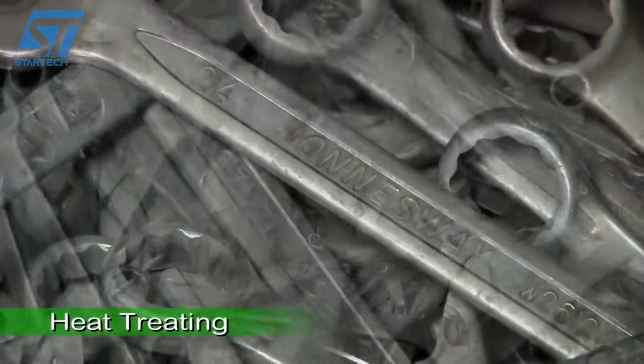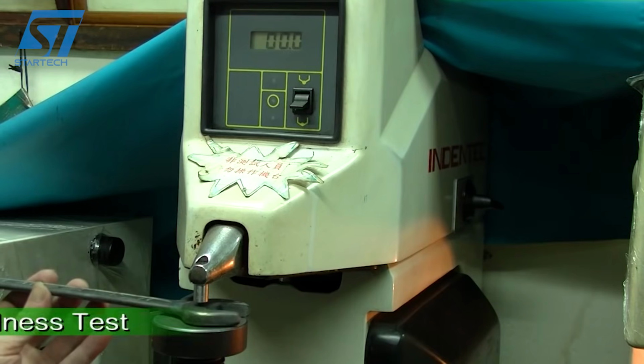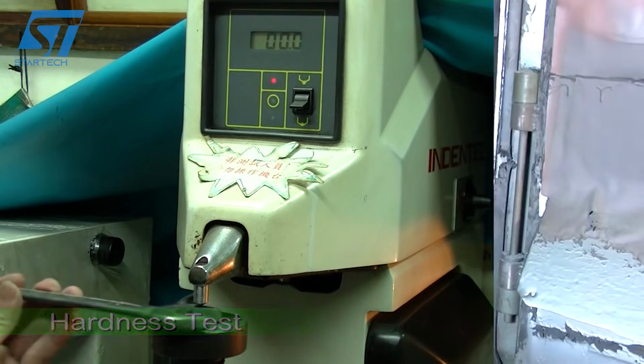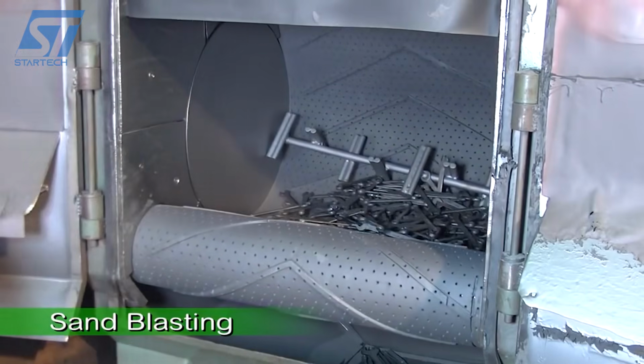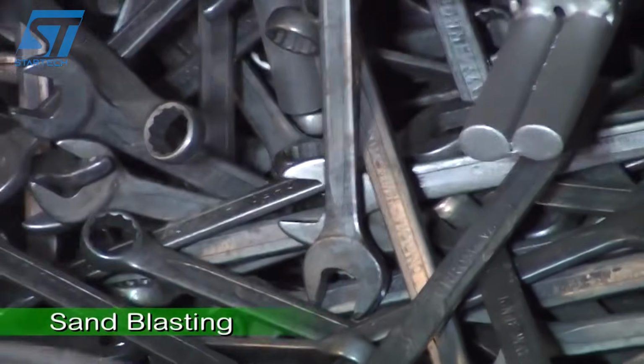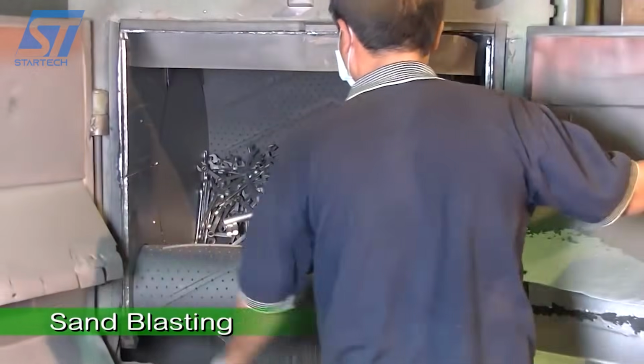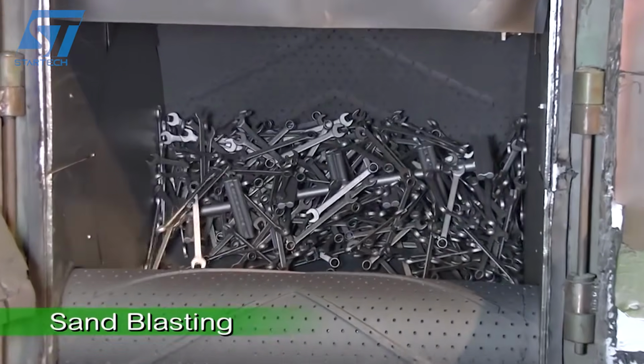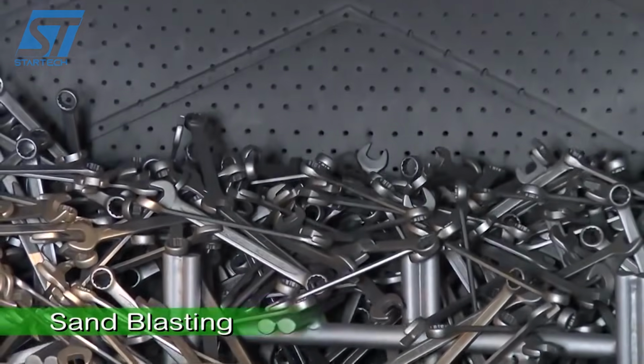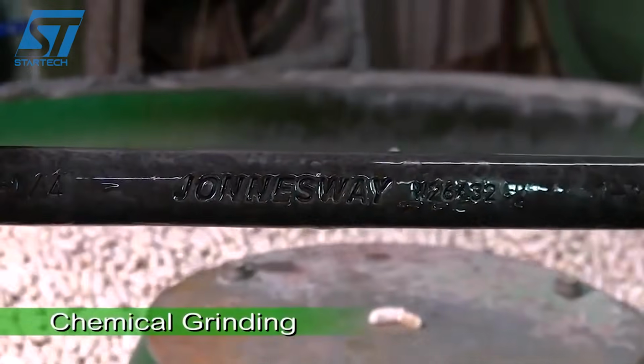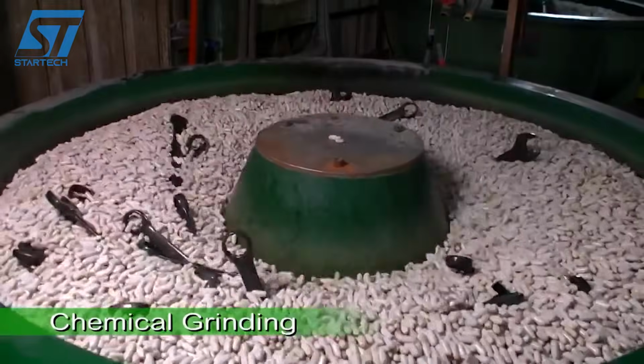But martensite alone is too brittle, so the wrench then goes through tempering, reheating it to a lower temperature and holding it there to reduce brittleness while preserving hardness. The target hardness for a professional-grade wrench typically falls between 40 and 45 HRC on the Rockwell scale, hard enough to resist wear, but tough enough not to shatter under a hard pull.